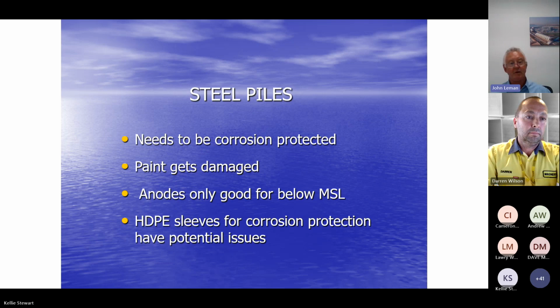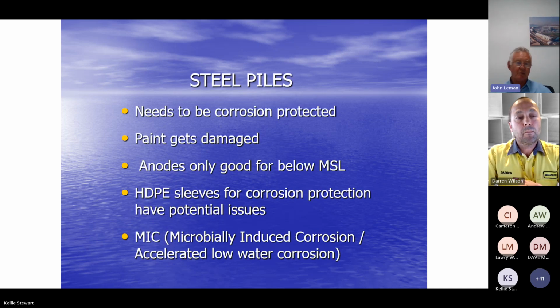More popular of late has been putting HDPE sleeves over steel piles, which work by driving into the bed and sealing the top. So we work on oxygen depletion. My issue with that is that we never know what's happening behind the HDPE sleeve. If you've just got a very small pinhole in the pile somewhere, then during the day when it heats up, it blows the air out, and then during the night it sucks in fresh air, so we won't necessarily get that oxygen depletion if there's any flaw in that sleeve installation.